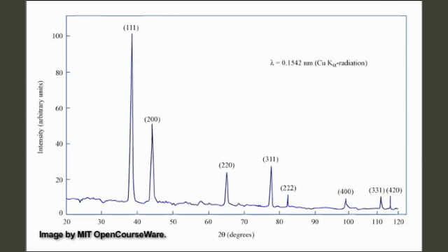So you're plotting intensity as a function of 2 theta. Somewhere along here, at about 38 degrees, you have satisfied the Bragg angle and you get constructive interference. When you move off of 38 degrees, destructive interference reigns supreme and you get almost no reflection. Then you get to the right angle for 200, you get reflection. Well, all you get is these lines. You don't get these numbers. These numbers you don't get for free.